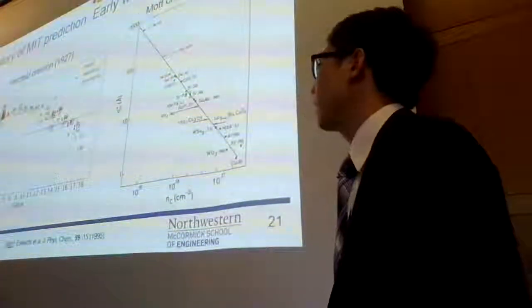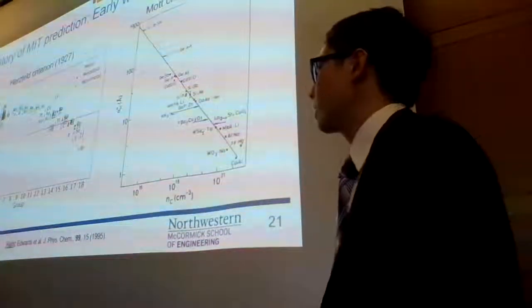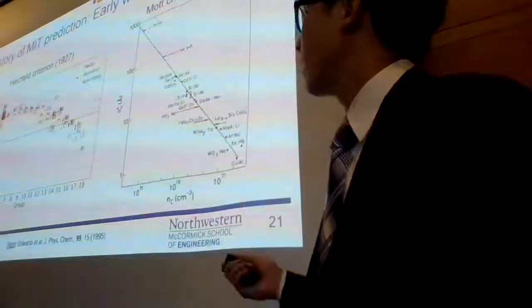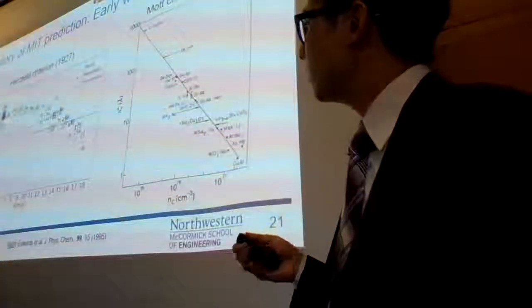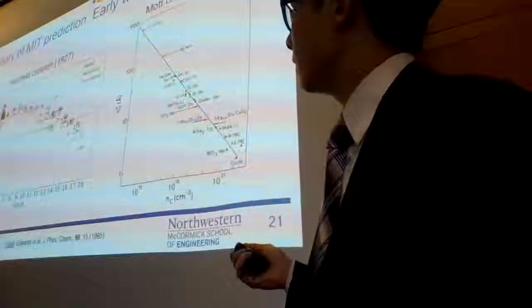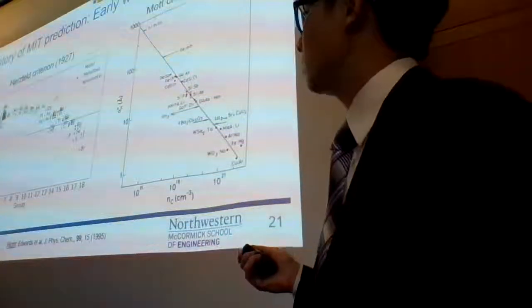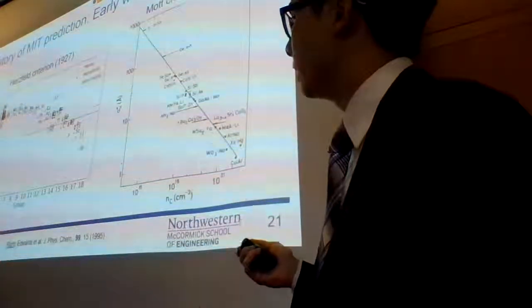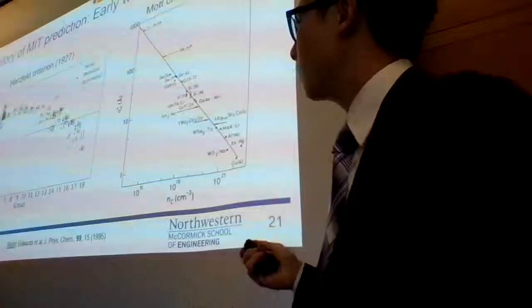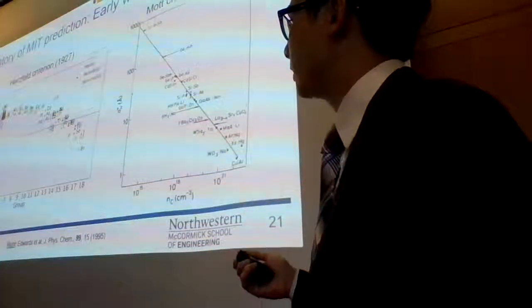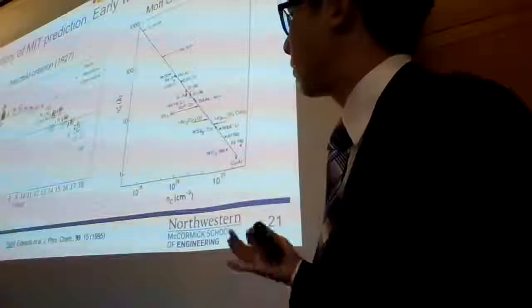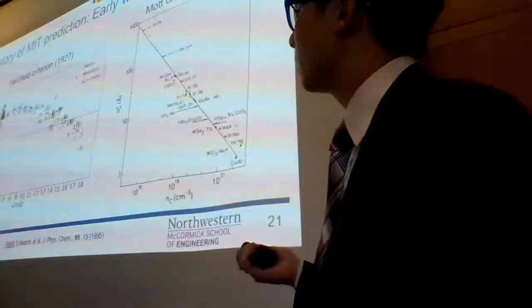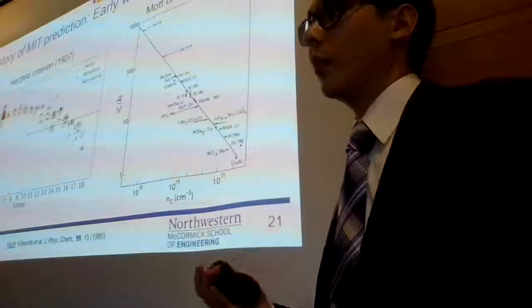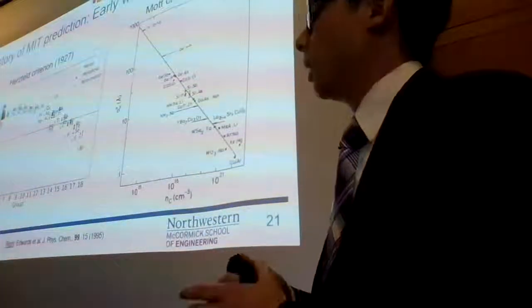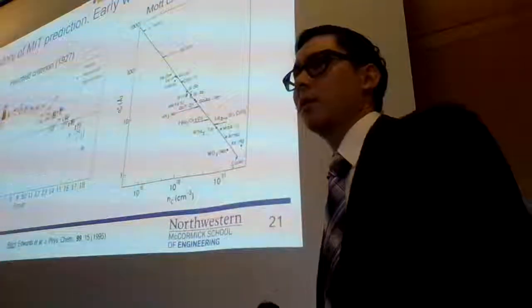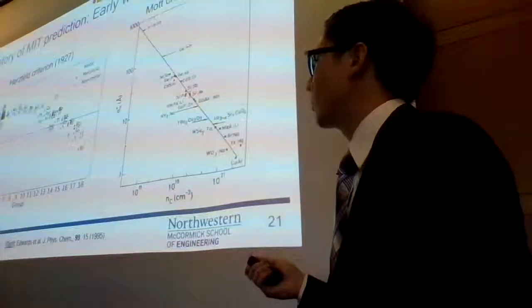First, some background on other people who have defined what they wouldn't call classifiers, but essentially classification schemes for separating metals and insulators. Going back to the early part of the 20th century, Herzfeld came up with the Herzfeld criterion, relating the polarizability of the elements to their molar volume, essentially stating that when the molar polarizability over the molar volume became equal to 1, there was a transition from a metal to a non-metal. You could see that it worked fairly well, given that there was no quantum mechanics involved at all. It does predict a few metal-insulator transitions in the periodic table, in terms of high pressure for hydrogen, or volume expansion of mercury, but it was never applied to compounds, and it misses things that are on the borderline.